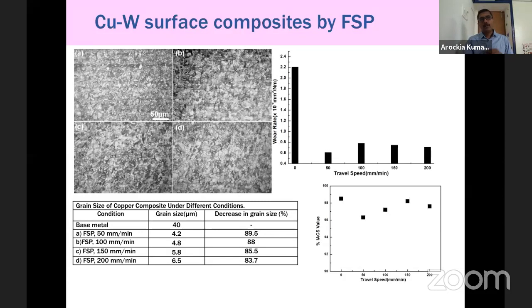And we also looked at the copper tungsten composite, which is one of the successful copper composites available in the market. The problem with the composites available in the market is that they have very poor electrical conductivity, because tungsten has very low electrical conductivity. So when you add tungsten into copper, copper's conductivity also decreases. What we were trying to do is, instead of putting more tungsten, put less tungsten and then improve the strength by FSP. Is it possible? Once again, the wear rate is significantly reduced, and at the same time the conductivity is not decreased to that extent. The conductivity is decreased only around 1 to 1.5%.